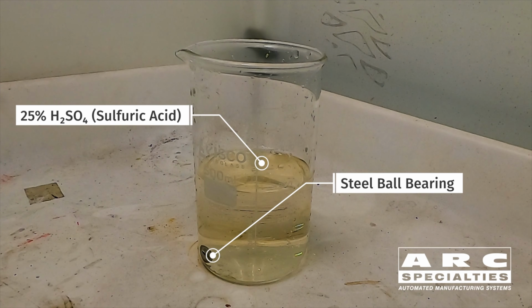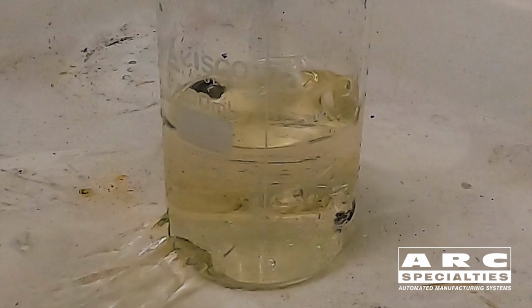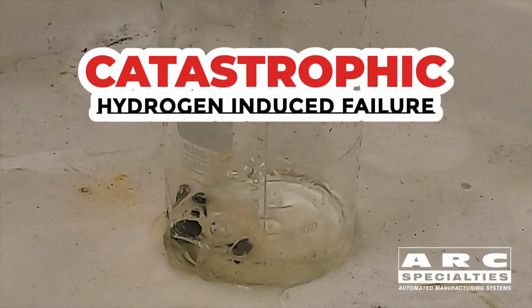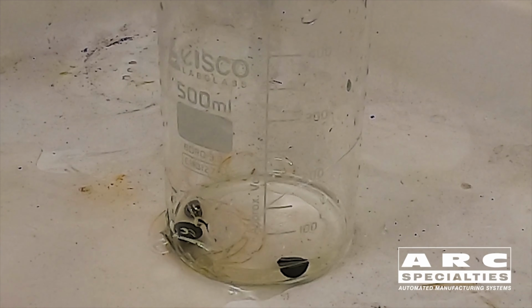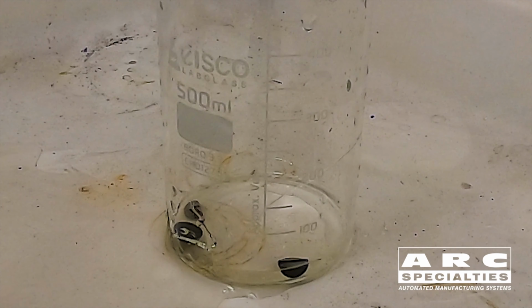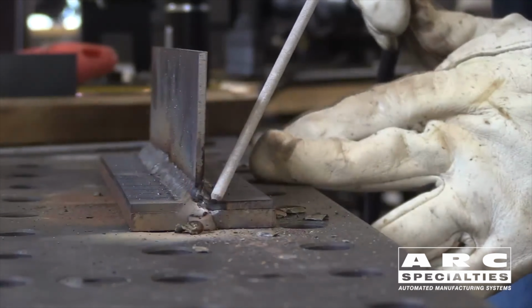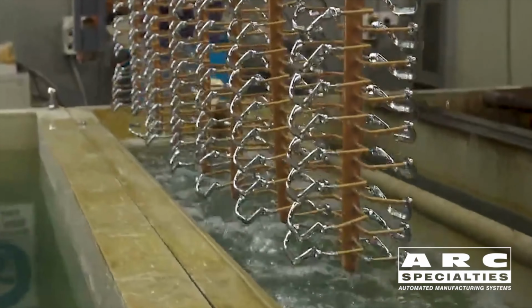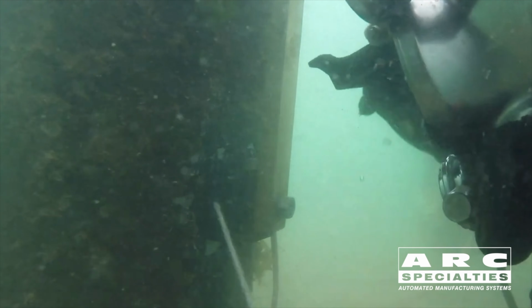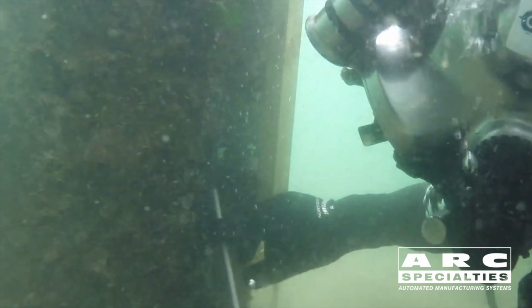Pretty quickly we see some corrosion. We're producing hydrogen, goes into the grain boundaries, and you see we have catastrophic failure in a very short period of time. So this is just one way you can experience hydrogen-induced cracking. You can also see it from moisture in electrodes. You can have hydrogen cracking from electroplating, and you can have hydrogen cracking from excessive cathodic protection on subsea parts.